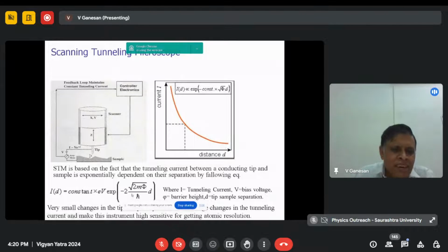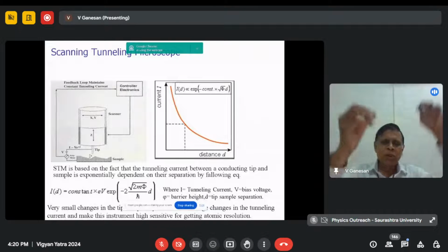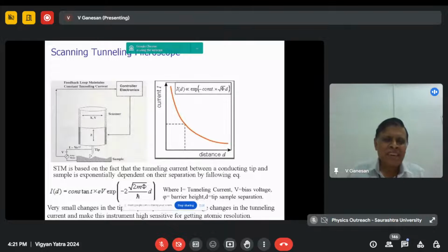There must be an occupied density of states in the tip, and an unoccupied density of states in the sample. Therefore, there's a probability of tunneling. Nevertheless, since it is an exponential dependence, it becomes very sensitive. If you move your tip from 1 Angstrom to 2 Angstrom to 3 Angstrom, the current will fall roughly exponentially. So it will be a very fast decay, and its selectivity is very high. That is why, in simple sodium chloride at 5 Angstrom distance, it is easier for you to detect it as you go from sodium to chlorine to sodium to chlorine.